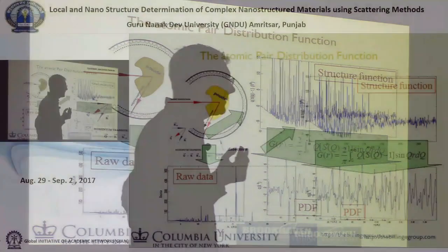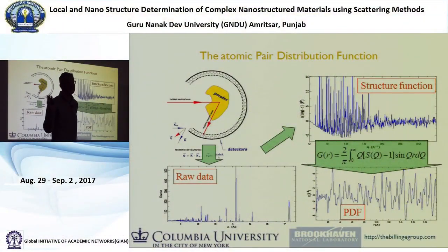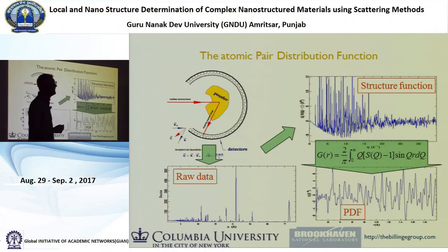Now, this function has one axis G, and it has another axis R. So G is a probability. By the way, if anyone has questions, raise your hand and ask questions anytime. Happy to be interrupted. This has a probability on this axis and distance on this axis. And the probability measure is the probability of finding two atoms separated by this distance. So this is a high number. So there's a high probability of two atoms in this material being separated by this distance, which is 2.75 angstrom.